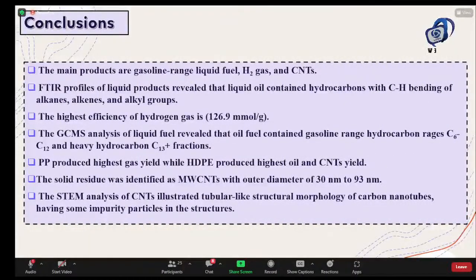The main products are gasoline range liquid fuel, hydrogen, and carbon nanotubes, especially multi-walled carbon nanotubes. The FTIR profile shows carbon-hydrogen bonding of alkane, alkene, and alkyl groups in the liquid product. The highest efficiency of hydrogen gas was 126.9 millimole per gram, which is reasonable compared to photocatalysis or other methods. GC-MS analysis shows the presence of carbon 6 to carbon 12 and some heavy hydrocarbons with carbon chain 13 and plus.